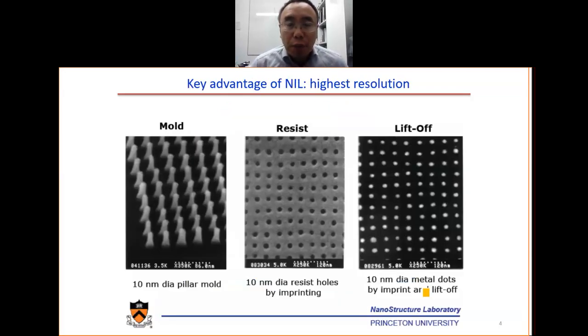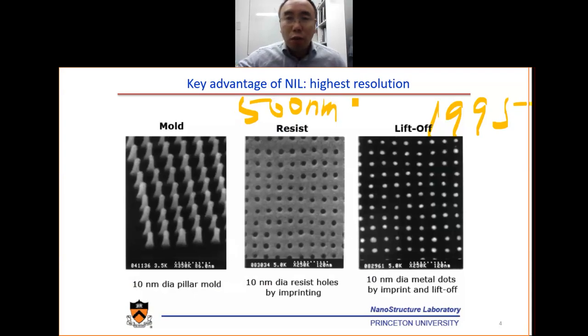The main advantage of nanoimprint lithography is the very high resolution. As you can see here, this is a 10 nanometer mold etched into the silicon. These are 10 nanometer holes imprinted into the resist, which is PMMA. This is the PMMA polymer film. Then we do the metal deposition. We do the chromium deposition and the lift off. So we get 10 nanometer diameter metal dots. This was done around 1995. At that time, the semiconductor industry's feature size was about 500 nanometers. So in the middle of the 1990s, the industry got down to 500 nanometers. But for nanoimprint, it goes to 10 nanometers easily. So this was very exciting in the 1990s.